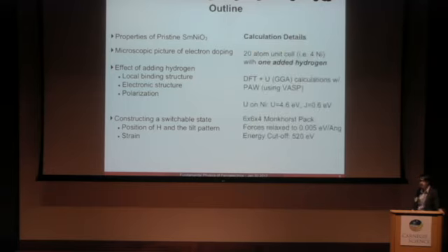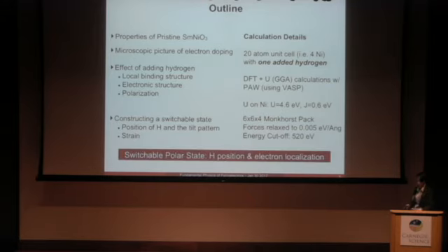These calculations are done in a pretty standard fashion using VASP. Because samarium nickelate has a PBNM or P21/N structure, you have a 20 atom unit cell with 4 nickel per cell. And this hydrogen doped structure we'll be looking at is 1 added hydrogen into this 4 nickel cell. So again, the main goal I want to get to in this talk is looking at a switchable polar state that is not only based on the inclusion of hydrogen into the lattice, but the fact that we have electron localization and an actual purely electronic dipole in the structure.